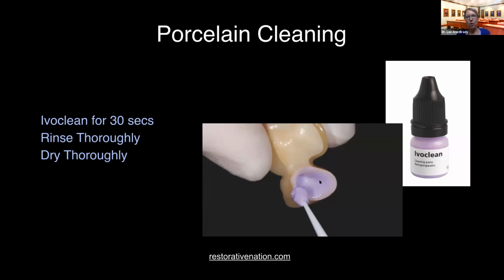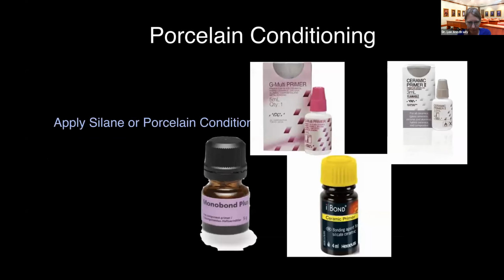And so this is what you're going to do for zirconia, metal, resin. And you can do it for glass ceramics if your lab already etched for you. And then you need to follow that with a primer. So there are two priming chemistries today. One is silane. Silane primes all of the traditional glass ceramics: lithium disilicate, feldspar, lucite reinforced. Or MDP. MDP primes the glass ceramics, but it also primes zirconia, metal, and resin. So if you want one bottle, buy what they call a multi-primer. So Monobond Plus, G-Multi Primer, Bisco makes a multi-primer, Panavia makes a multi-primer. Be careful, if the bottle says ceramic primer, it typically only contains silane, and that won't work on zirconia, metal, or resin. You need MDP for that.